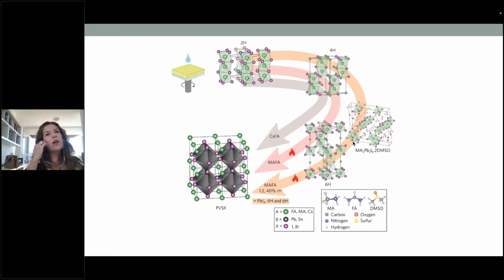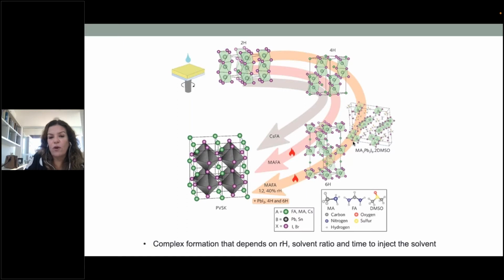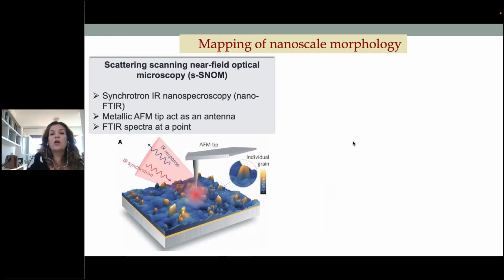And the question was, even at the end of this process, do we still have these hexagonal phases in the film? Because we don't want them. And if they're still in the film, can you see them? Can you find them in the film? So also using the synchrotron, now another beamline, here using the nano-infrared. The nano-infrared, as far as I know, is going to be open for submissions in the next month.